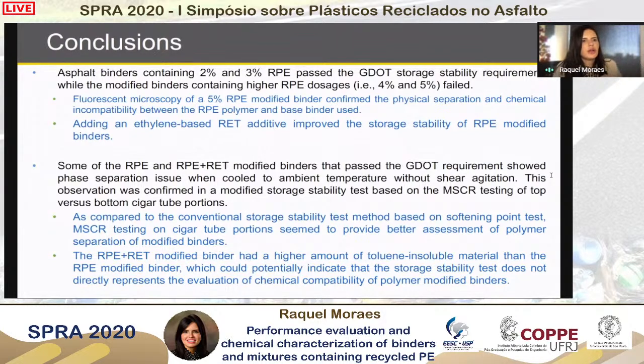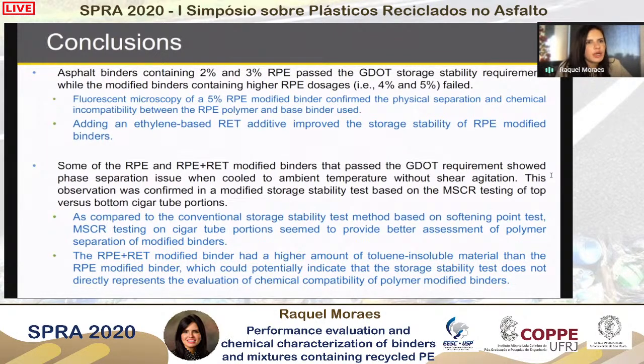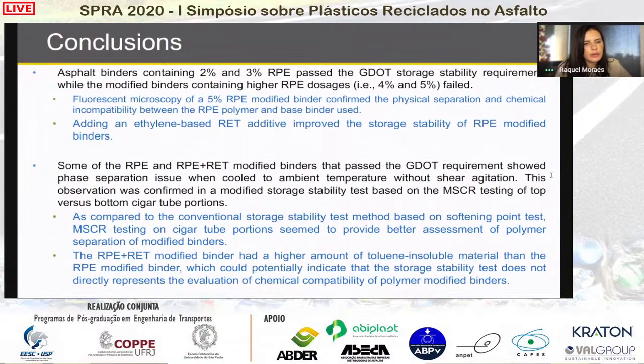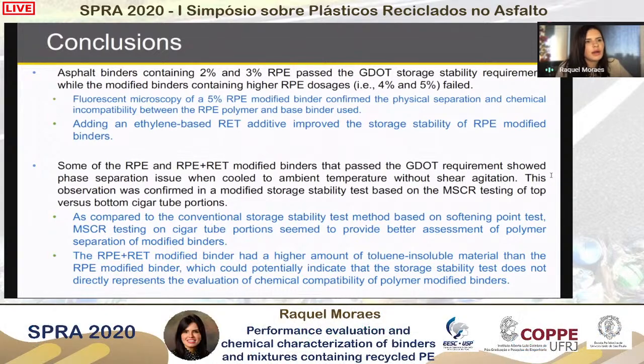So the overall conclusions of the experiment, I will go briefly, is that we can see that a higher percentage of recycled polyethylene will not give us a passing criterion according to the Georgia Department of Transportation, and that the softening point testing results after storage stability can be misleading. So therefore, the MSCR test is a more reliable way of evaluation of polymer separation after the cigar tube storage stability.